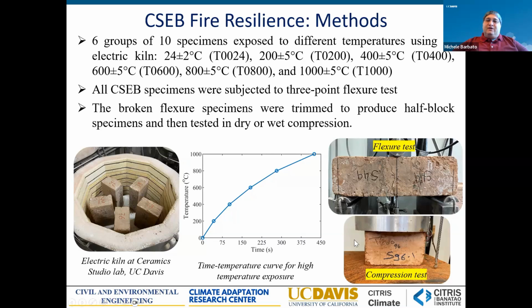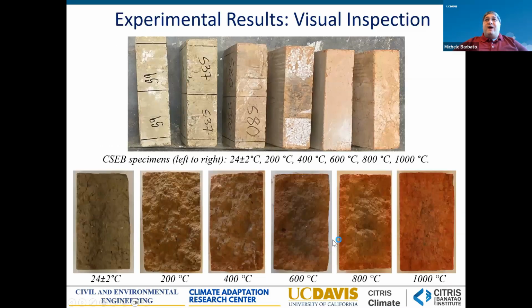After these, we took the blocks, we tested them first on a 3-point flexure test, and then we took the 2 halves obtained from that test, we trimmed them, and we used them for compressive strength in dry and wet conditions. So what we found? From a visual inspection, the first thing that we saw is the change in color that we showed also in the previous video.